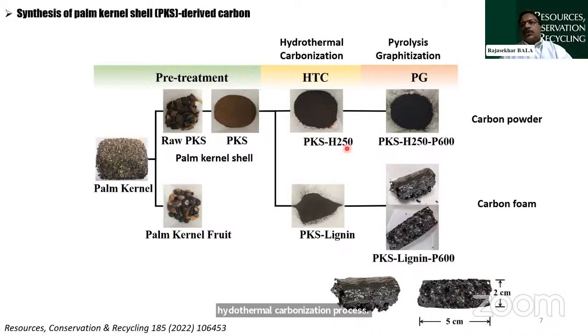This is a conventional hydrothermal carbonization process. You heat it up to 250 degrees Celsius, you get the carbon powder, and unfortunately, this pathway does not produce lignin. It's lost, or you don't have a significant amount of lignin. So instead, we modify the conventional hydrothermal process. This is one of the components of the novelty of our work. When you modify the conventional hydrothermal carbonization process by adding some alkali, followed by acid, you get this lignin in a large amount. Then you can process lignin through pyrolysis, which will lead to the carbon foam that we are talking about, which is a 3D macromolecular structure with a high level of porosity, high surface area and rigidity, so that it can be regenerated and used a number of times for this kind of application in terms of removal of CO2. These are the steps involved in the synthesis of carbon foam.